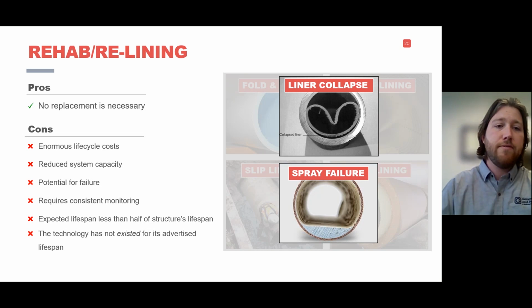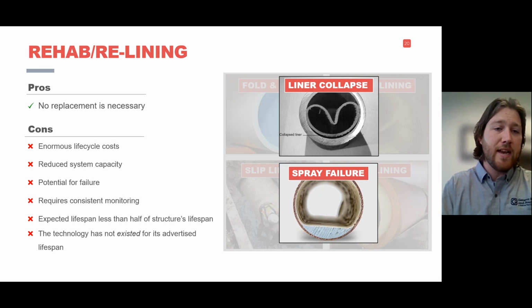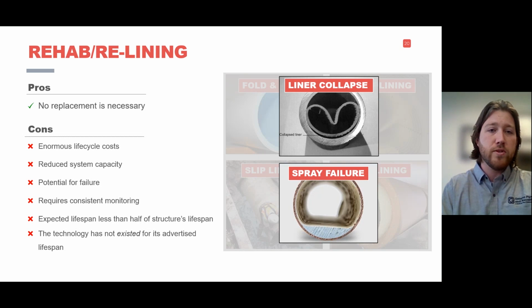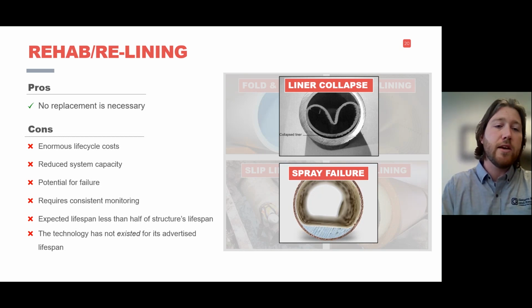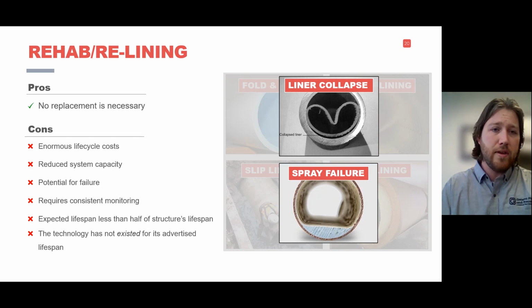However, considering the fact that this had an initial installation, you're essentially just adding that on top of what that pipe was supposed to cost in the first place, increasing the life cycle costs. Typically, as you can see in some of these photos, there's reduced system capacity, whether that's by decreasing the diameter of the flowable area of the pipe. There is potential for failure or delamination. Some spray linings can settle, and the expected lifespan is less than half of the structure's lifespan.